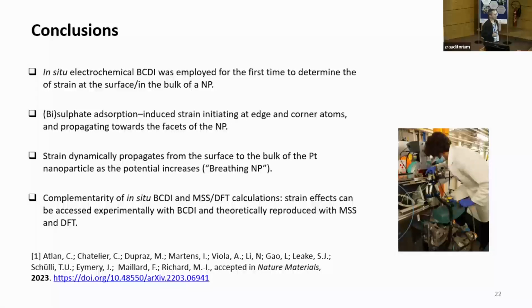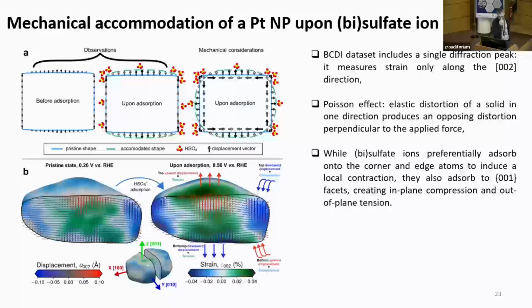Okay, so first question. We were working only along one direction. And this is, we think, what happens. Obviously, we get information on the displacement along the 001 direction here. This we are sure about: the movement of the corner atom in this direction. And we think this happens because of the Poisson effect. This in-plane movement leads to another expansion of the atoms out of the plane. So there will always be a compressive in-plane strain and a tensile out-of-plane strain.